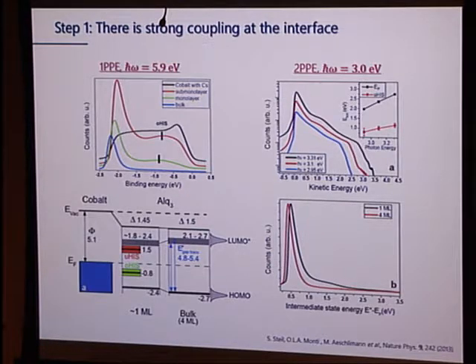So, the first thing that you need to see to convince yourself that there is a hope of getting such a fast spin filtering is that you have interaction between the molecule and the surface. There's a lot of data here. The main thing is really shown in the summary diagram here, where we did all the due diligence. We did the spectroscopy. We said we know where our molecular valence band is, the conduction band in bulk. Then when we get to the interface, we know it shifts a little bit. That's the renormalization. And then we see two new states. We call them HIS, for hybrid interface state, occupied and unoccupied, that only exist at the interface.